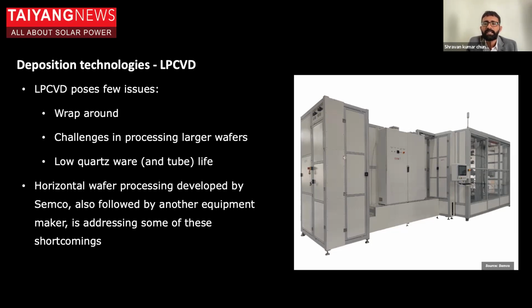So all this polysilicon that is sticking onto the quartz ware as well as the quartz tube grows to a level, and then during the processing, the stress created due to the mismatch of the coefficients of thermal expansion is strong enough to break the quartz tube as well as the quartz ware. So a part of the solution came from Semco. Actually, they started offering this solution 10 years back, which they developed for ribbon wafers, which do not have a fixed form factor.